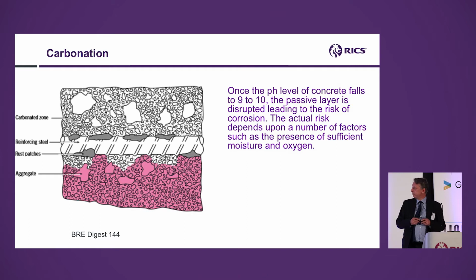So I've pinched this from BRE Digest 144. It's quite an old document. There's a newer version now, which I think is 244. But the principle is there. And what I wanted to illustrate here was the progression of this reduction in alkalinity over a period of time. So if we start with the top of the picture, the external surface, new building, good uncarbonated concrete, plenty of protection to the steel. But over a period of time, depending on the porosity of that concrete, the alkalinity drops. And that zone of carbonation gradually extends over a period of time and could reach a point where it reaches the steel.